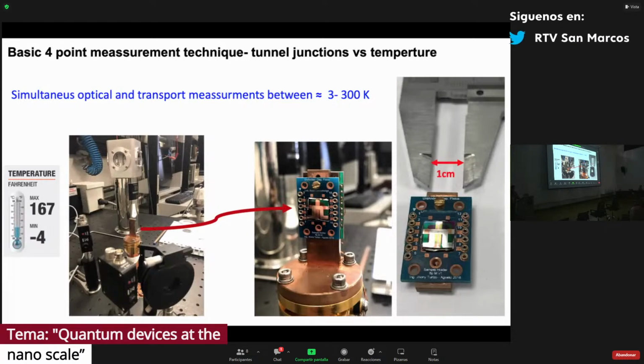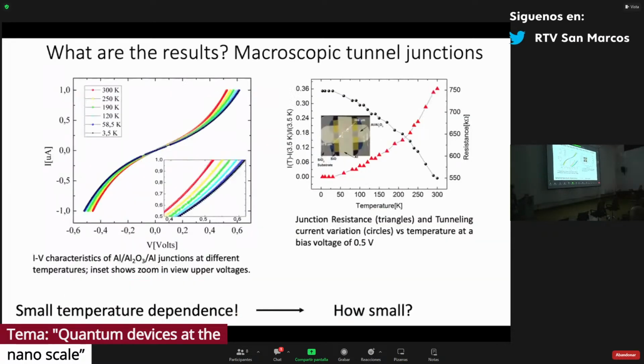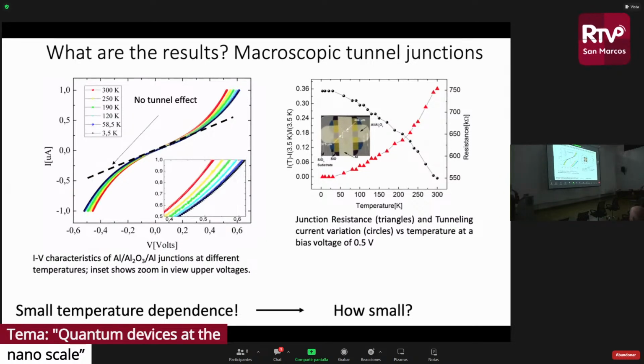These are the results. In order to know if you have a tunnel junction, the IV characteristic has to be curved like that. And there is also a small temperature dependence, changing with temperature between 3.5 and 300 K. Important information here is that it works at room temperature. That's important, that these devices can function well at room temperature. And normally, we tell the students, go down in temperature so that you don't damage your device, but we realize that that's not necessarily true all the time.